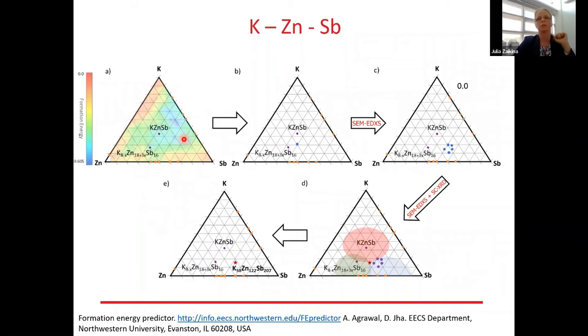And we use a similar approach, similar to the sodium system, but rather than randomly screening all of the compositions, we use the formation energy predictor, so we can calculate the formation energy for any given composition within this ternary system. This predictor uses machine learning approaches to predict the formation energy using a DFT-calculated formation energy training set. And as chemists, we should take it with a grain of salt, but at least it gives us some idea of what other compositions we can try.